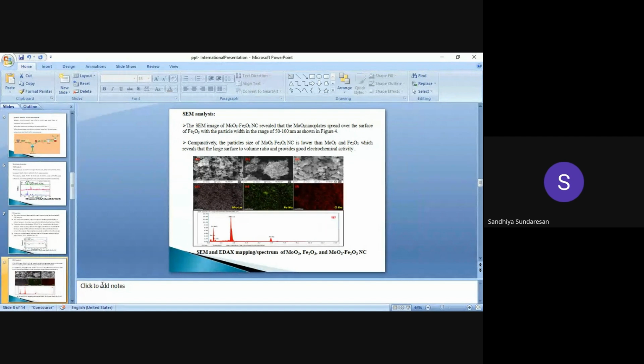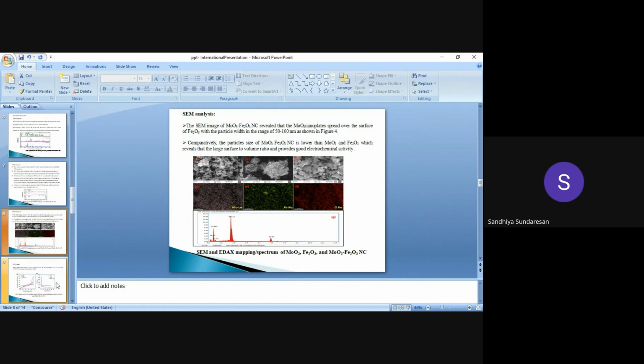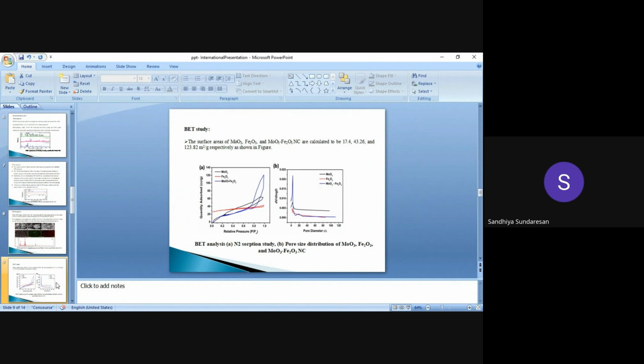Nanoplates were presented in the range of 50 to 100 nanometers, and comparatively the particle size of the molybdenum dioxide and iron oxide nanocomposites is lower than molybdenum dioxide and iron oxide. A large surface-to-volume ratio provides good electrochemical activity. And this is the BET study, the Brunauer-Emmett-Teller method. The surface areas are calculated as 17.4, 43.26, and 123.82 square meters per gram, respectively, in this figure.